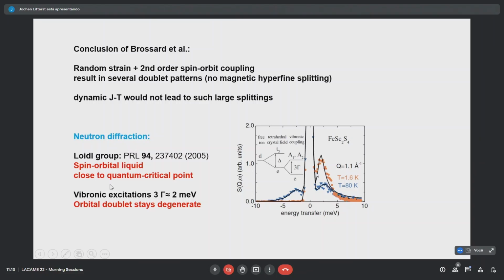Now, some years later, it was studied again, now by neutron diffraction, by the group of Loidl in Augsburg. And they found out, at least they claim, it is a degenerate orbital state. However, what you have there has liquid-like dynamics at low temperatures. So here it's not only the spin, it's the spin coupled to the orbital state. So it's a spin-orbital liquid, close to a quantum critical point. Their fluctuations are fast, and therefore you don't see magnetism.